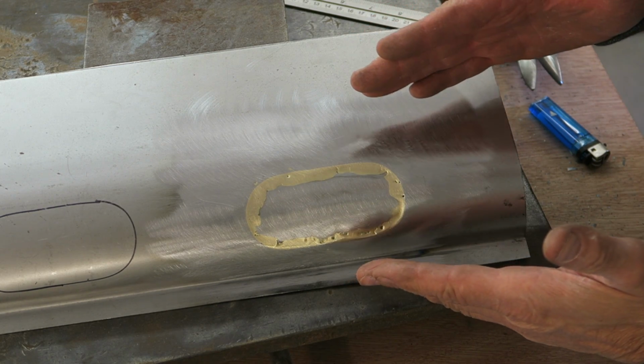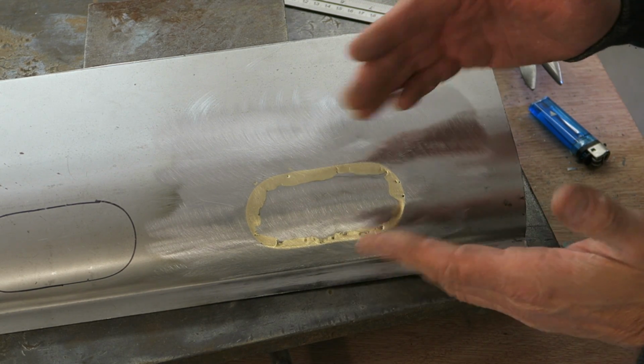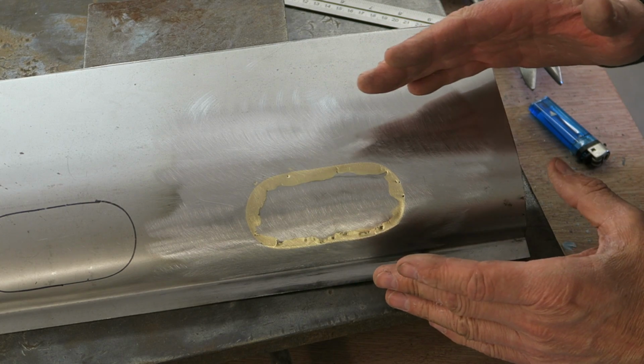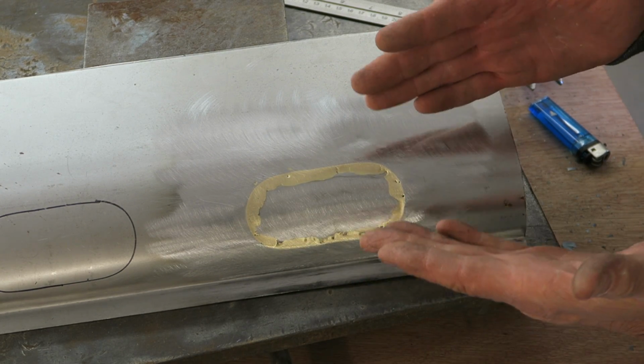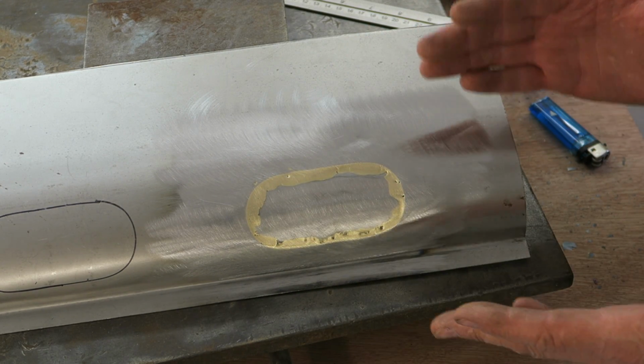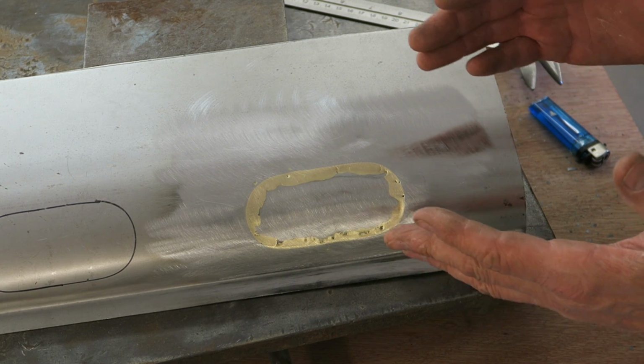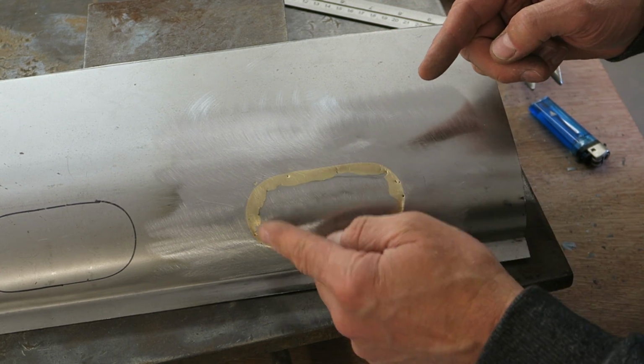All cleaned up with a grinder and a clean and strip wheel. From a structural point of view, the repair's good. The brass has flowed into the joint. It's a lap joint. It's really strong. There isn't going to be any problem with that. From a corrosion perspective, it's sealed up with brass.